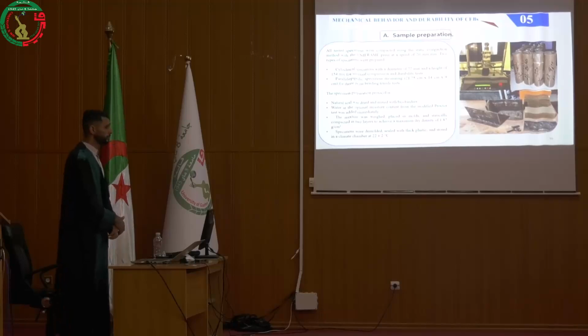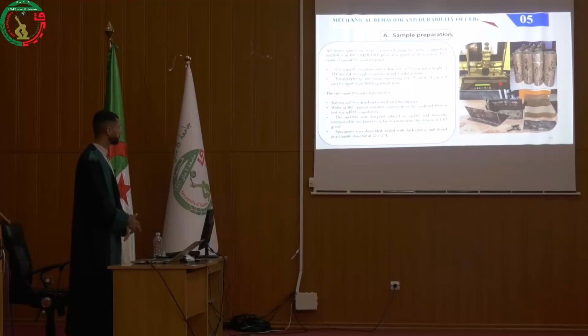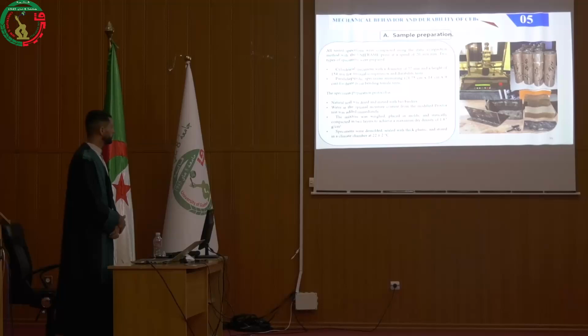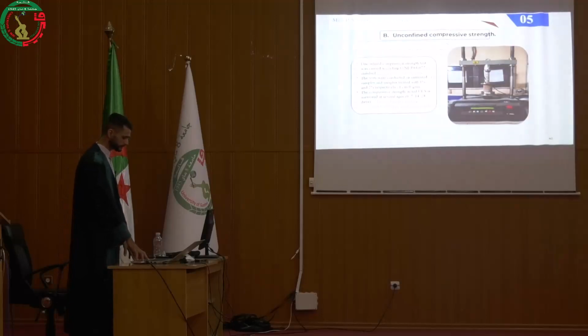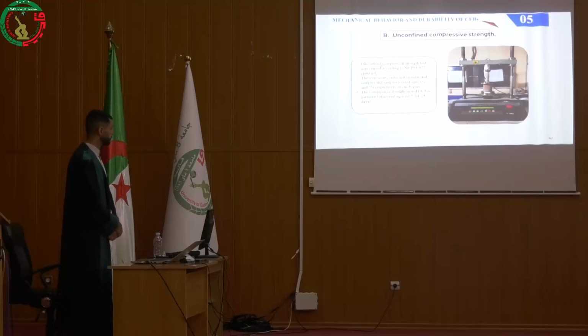The specimen preparation protocol is: natural soil was dried and mixed with bio binders. Water at the optimal moisture content for the modified Proctor was added immediately. The mixture was weighed, placed into molds, and statically compacted into layers to achieve a maximum dry density of 1.87 grams per cubic centimeter. Specimens were demolded, sealed with thick plastic, and stored in a climatic chamber at 22 degrees. The unconfined compressive strength test was carried out according to French norm standards. The tests were conducted on untreated samples and samples treated with 1% and 2% carob gum, respectively. The compressive strength, UCS, is measured at several ages: 0, 7, 14, and 28 days.